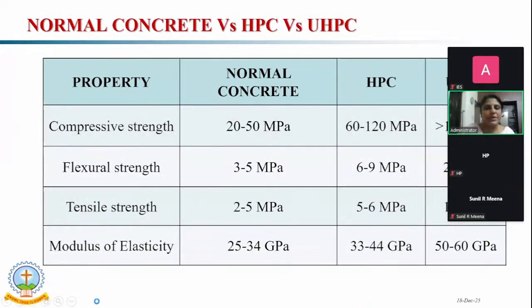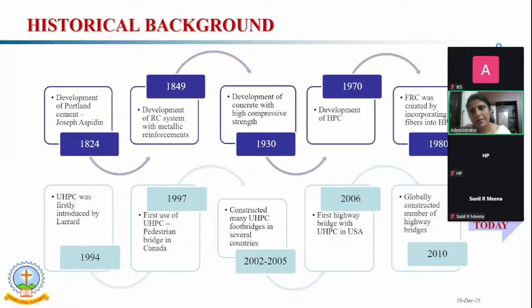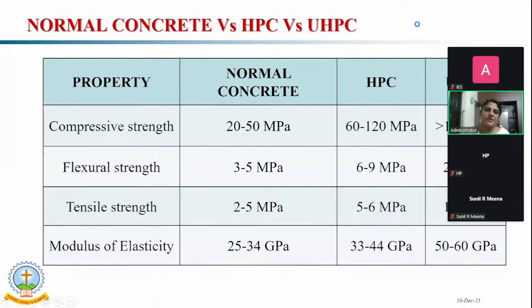If you compare the properties of normal concrete, high performance concrete and the UHPC, in the case of compressive strength, normal concrete, as you all know, is between 20 to 50 MPa. High performance concrete is between 60 to 120 MPa, but UHPC is above 120 MPa. Similarly, the flexural strength for normal concrete is 3 to 5 MPa, and for UHPC it is around 20 MPa. Tensile strength in normal concrete is 2 to 5 MPa, but in UHPC it will be up to 15 MPa. Modulus of elasticity is 25 to 34 GPa for normal concrete, but for UHPC it will go up to 50 to 60 GPa.